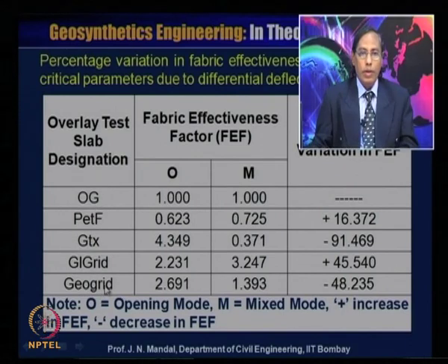This is geogrid, glass grid, geotextile, polyester, open graded, and you can see that the fabric effectiveness factor is also high for glass grid and the geogrid, although in the mixed mode there is variation. Also in geotextile you can see that the effectiveness factor is better in opening mode, but in the mixed mode it is on the lower side. So overall, the glass grid gave a good result in terms of the mixed mode as well as the opening mode.